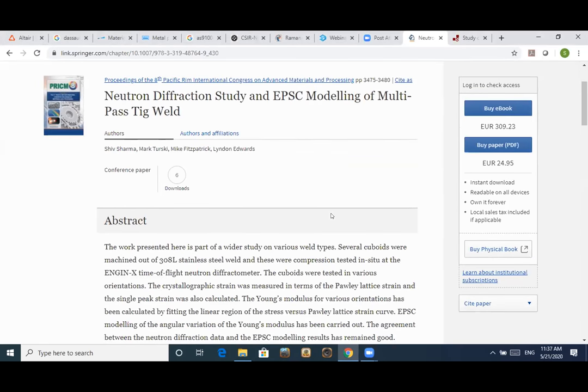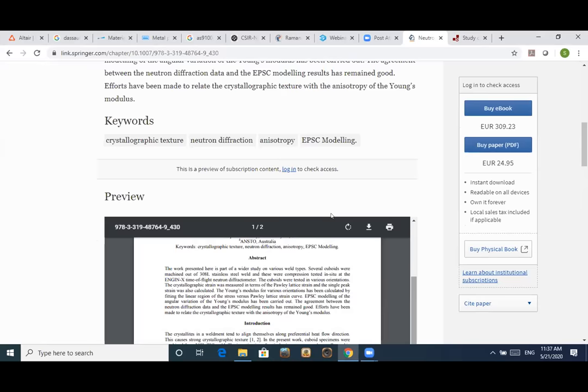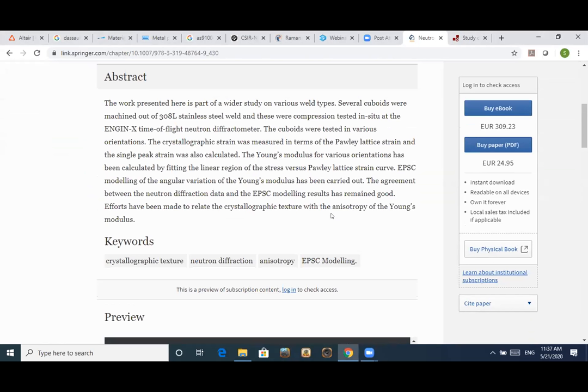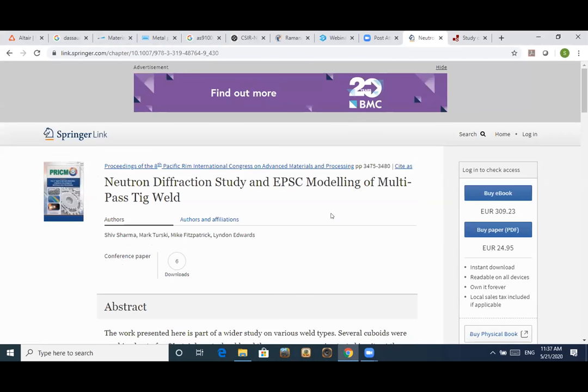Fantastic. I would like to see this paper because I think you have done something on the residual stress. Is it on the residual stress? Actually, within my group, the work on residual stress was also being done. For example, that was called a bead on plate geometry. So they normally take a base plate, then deposit a weld bead onto that, and then do the neutron diffraction across the plate. For example, parent, then weld bead, then parent. So it gives the distribution of residual stresses across the bead. But my work was more on the anisotropy part of the weld metal.